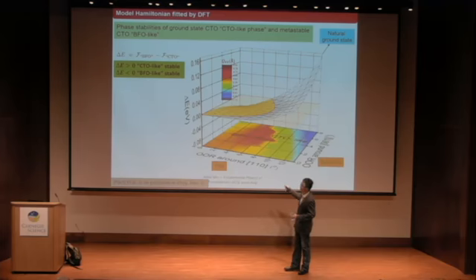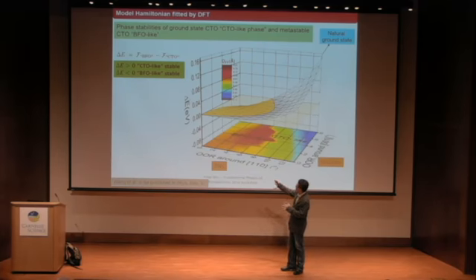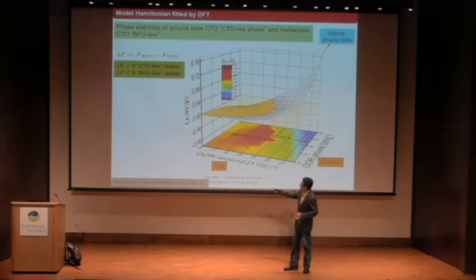This yellow plane is the zero plane. If delta E is larger than 0, then CTO-like is stable because CTO is smaller in energy. If delta E is smaller than 0, then the BFO-like phase is stable. This is a natural ground state at this point.